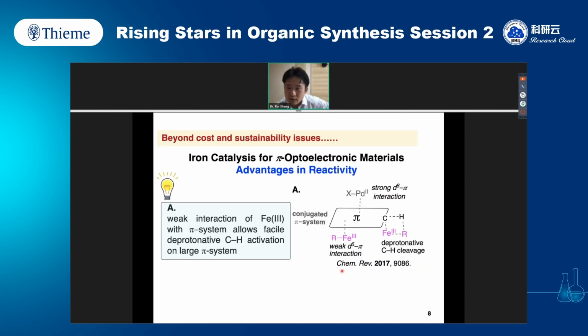With this reactivity discovered, and also my experience working on electronic conjugated materials, I was thinking about where we should go here. Beyond the sustainability and cost issues we always emphasize for iron catalysis, from a chemical point of view there are inherent advantages of iron catalysis for conjugated material synthesis. Iron-3 has very weak interaction with the pi system, so the deprotonative CH cleavage is suitable for large pi conjugated molecules. And the selectivity is always determined by the acidity of the CH bonds.